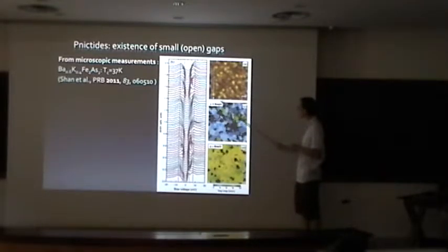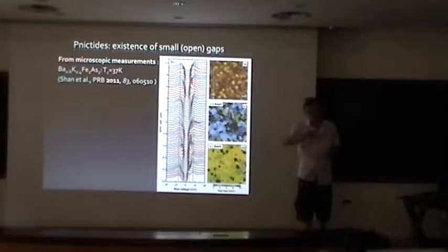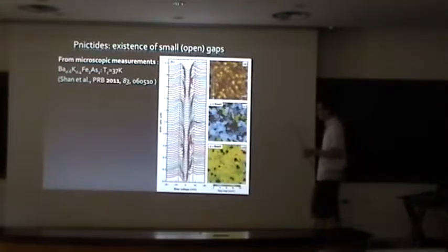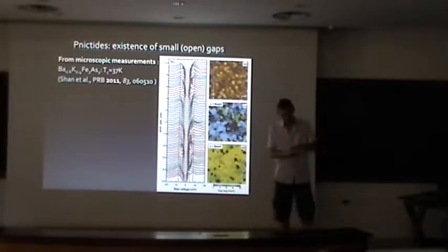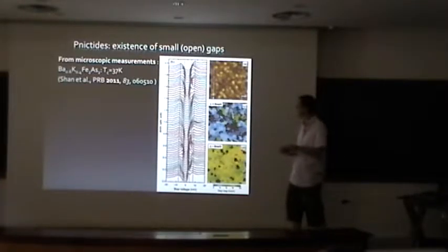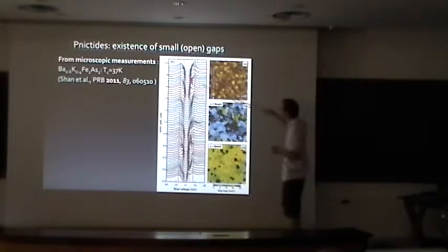So here it's 2 nanometers, so you see this is a rather big area of the sample. Then they scan on a line on this surface, and these are the different spectra that you observe on different places of the surface of the sample. So it's quite important to see that, because if you do a planar junction, for example, it's never perfect, and it's difficult to see if the result is just coming from the spurious average of the features you want to see, or whether it's something really intrinsic. At least with STM, you can see how reproducible are the features that you observe.